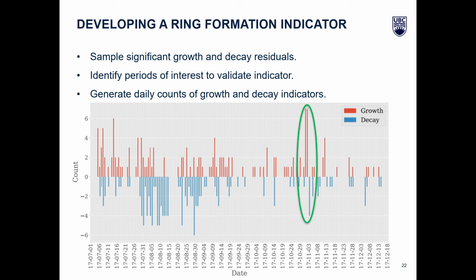Then we generate daily counts from both the growth and decay residuals, which we plot over the experimental trial. The highest daily count of growth indicators is 7, and this occurs twice in consecutive days, which are circled in green. After these 2 days of high growth, we see a day with significant ring decay. Now let's observe this period more closely and use the raw images to try and validate the indicator.